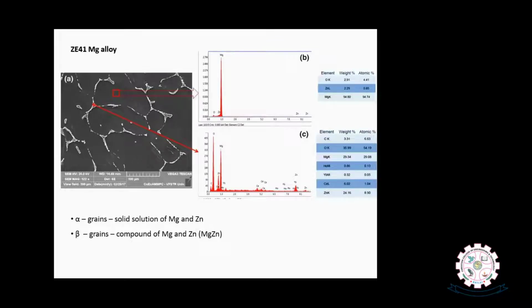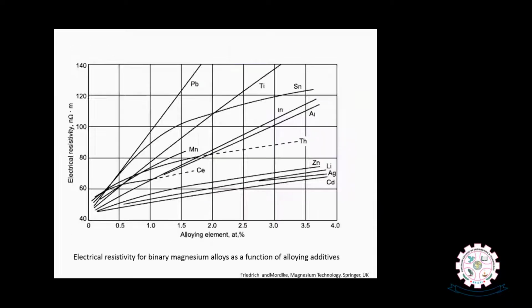And this is another typical microstructure of ZE41 magnesium alloy, where zinc 4% and rare earths 1% is added to magnesium, and you can see clearly the development of intermetallics at the grain boundaries, and also alpha grains, which are the solid solution of magnesium and zinc. The corresponding elemental composition also will demonstrate the presence of intermetallics at the grain boundaries.